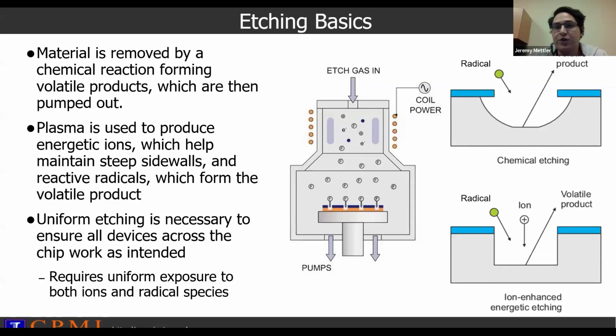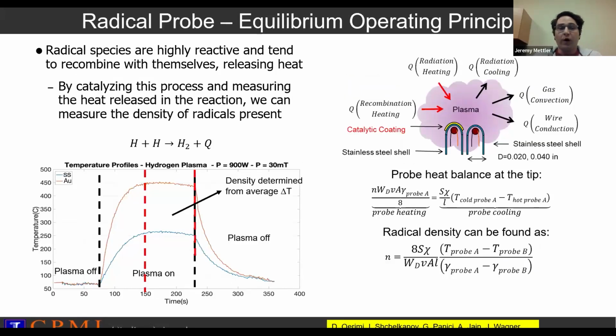And so it's difficult to ensure from a design standpoint that you're getting a uniform flux of radicals across an entire workpiece. And so the goal of this work was to investigate whether we could come up with a way to measure radicals in situ and in a way that's spatially resolved. Fortunately, there's some work that's been done to this effect in the past with other types of radicals. Not fluorine, which is used in etching, but things like hydrogen, nitrogen, and oxygen. And that's using radical probes.